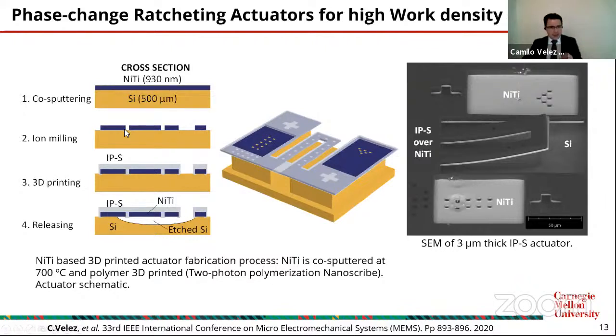Then you pattern the nickel titanium using ion milling. After you pattern the material, you 3D print the polymer. The polymer that we selected was IP-S from Nanoscribe, because of the stress that we want to generate. After you 3D print, it looks like this for a single beam actuator. You release or etch some of the silicon underneath the actuator, so you have a floating cantilever that is bending up. When you apply current, as you can see in this picture, the cantilever bends down, and that's how you generate the force.